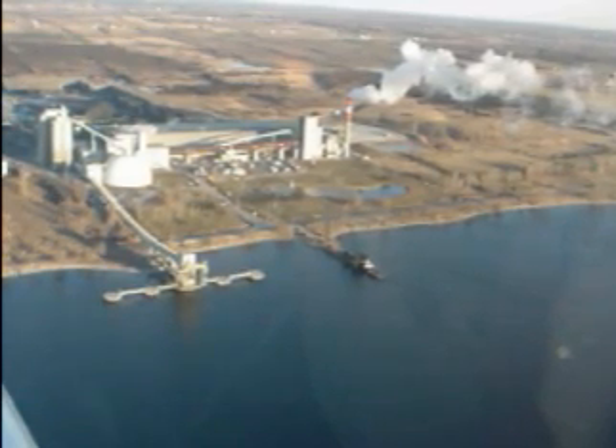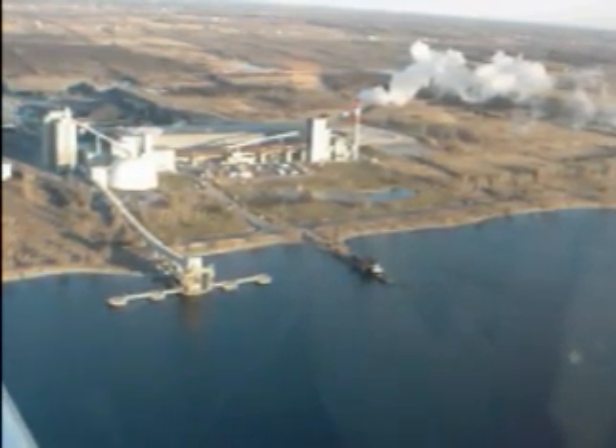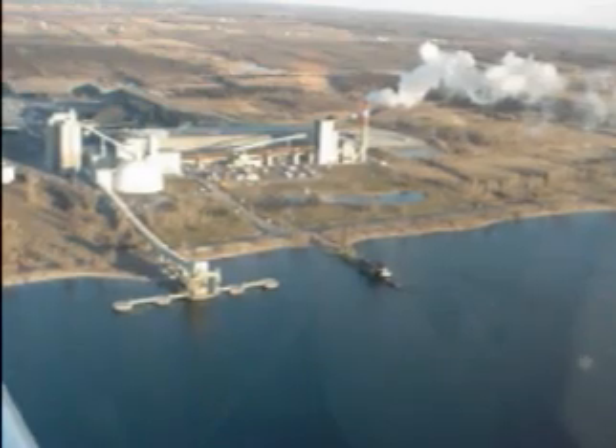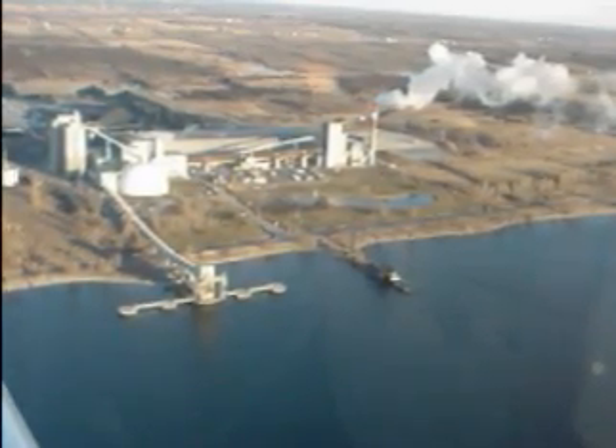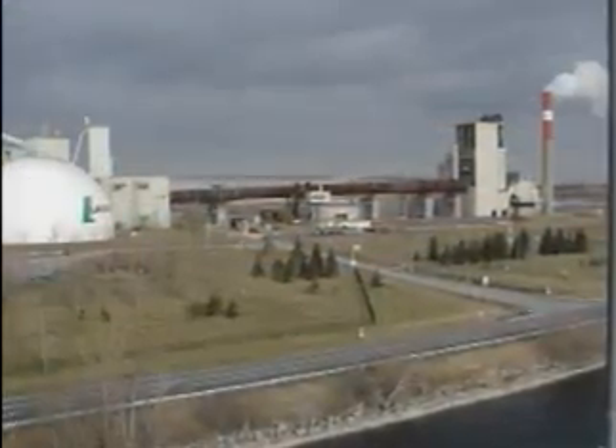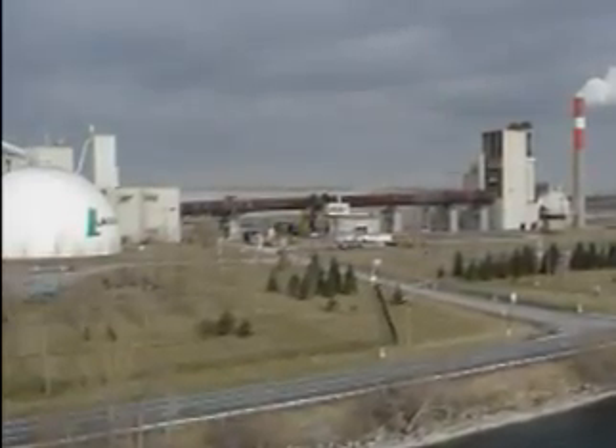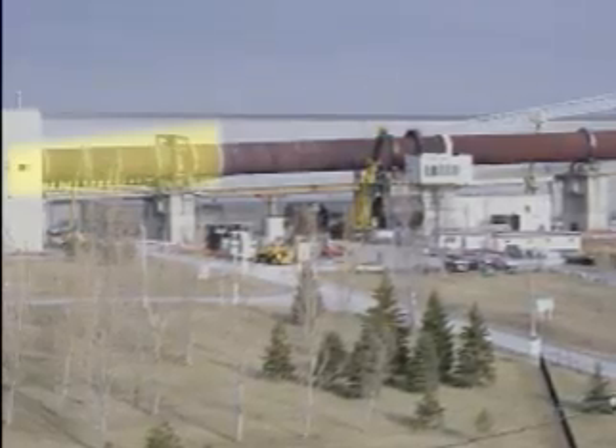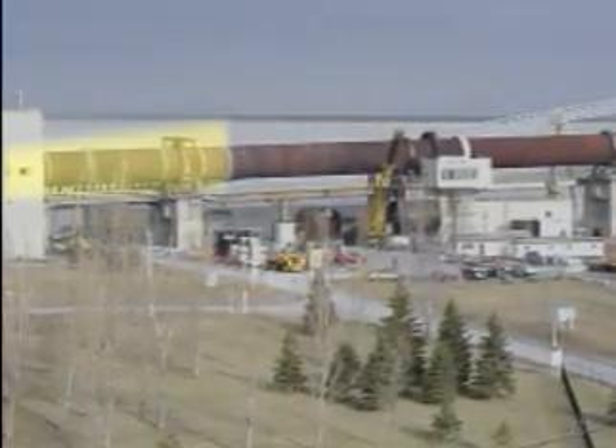After running for a quarter century, the 655-foot-long kiln experienced frequent refractory failures in the burning and upper transition zones. This led to reduced operability and unplanned shutdowns. In fact, more than 130 feet of the kiln at the discharge end had become severely deformed and was in need of replacement.